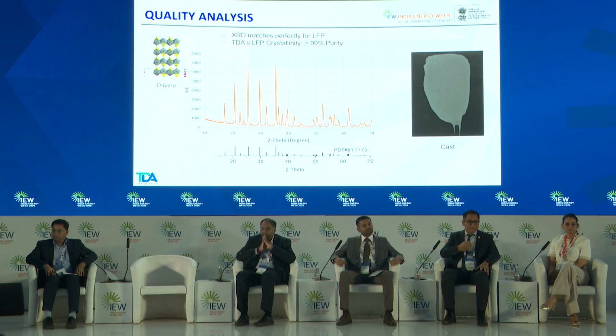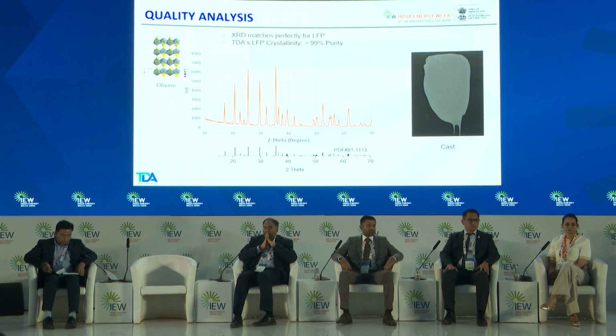This really shows what's called the X-ray diffraction, which is an analysis of the crystal structure of the material that we make. And what you see in the top graph is the scan of the X-ray of the material we make, and at the bottom is the standard. And as you can see, it matches extremely well. So we make our LFP with a 99+% purity. And then you make the LFP and you coat it onto a substrate in order to make the cathode material or the plates.